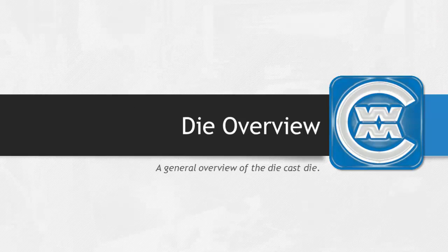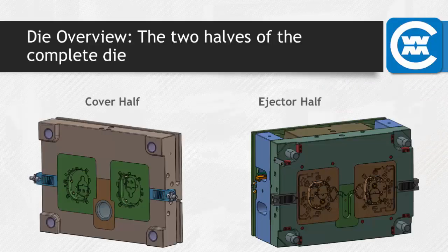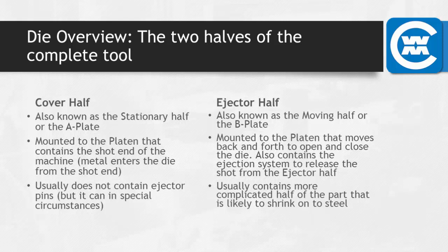Now we'll get into an overview of the die-cast tool itself. As we mentioned at the beginning, there's two halves that create the die-cast tool. The cover half creates one side of the part, and the ejector half creates the other half and contains the ejection system to release the part from the die. There's various names you'll see die casters refer to each half of the tool described above. As I mentioned, the cover half remains stationary on the die cast machine, and the ejector half moves back and forth to meet the cover half, and then pushes the part off the mold with ejector pins. That's why we typically design the ejector half of the part as the side most likely to stick to steel. If your shot sticks to the cover half, there aren't any pins to push the part off.